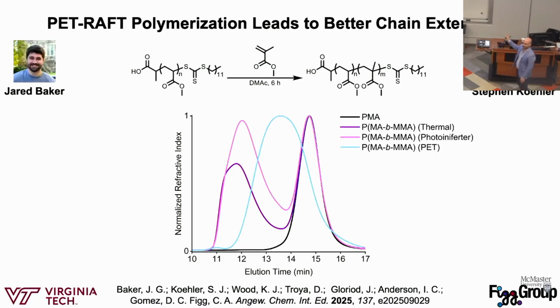We don't want a bimodal distribution in our GPC, but this is just a conventional AIBN initiation. If we do that photoiniferter technique by the Sumerlin group using UV irradiation that doesn't just completely blast everything and kill everything, you still get this bimodal distribution because it just doesn't work as well with the trithiocarbonate. However, this is one of the early PET runs that we did. With PET, we actually get some decrease in this molecular weight distribution. It's broad. There might be a little bit of this peak under this sort of broad peak. But the big thing is that we're seeing a shift of the distribution.